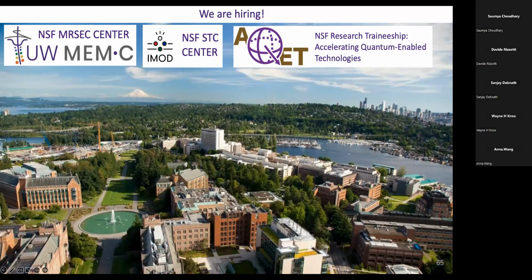I was wondering if you could talk a little more about the origins of the spectral wandering of the NV0 photon line and what exactly you attributed that to. Yeah, so very vaguely we attribute it to charging and discharging of nearby defects. When it's in bulk diamond, it's usually attributed to other nitrogen because we know that we have nitrogen nearby, and that's where you're getting that excess charge, and then nitrogen can exist in a neutral or ionized state.